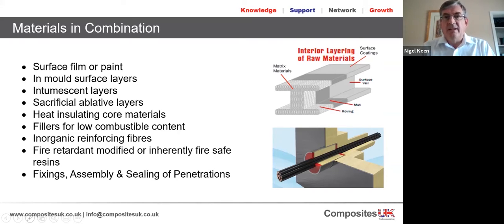You can put that paint into the mold and have that as a fire resistant gel coat. You can put it into a surface veil and actually have a layer immediately beneath your surface that is fire resistant and protects, if you like, a structural laminate or something underneath. You can actually build slightly thicker layers and you can decide, okay, I can usefully sacrifice, say, a third of my composite and still have enough structure to hold something up.